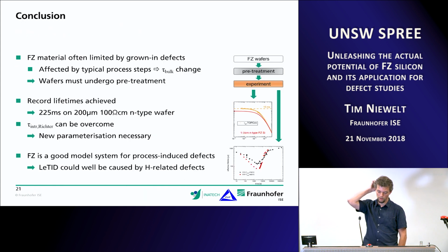With that, I would like to conclude the talk. In the first part, I was showing that float zone silicon sometimes has problems, and it's not as good as a lot of people are assuming it to be. But that can be solved by just pre-treating the wafers. And once we do that and then use a good surface passivation, we can get record lifetimes, actually the lifetimes that we would hope for float zone silicon to have. The Richter limit for intrinsic recombination can be overcome, so we do need an update on that.